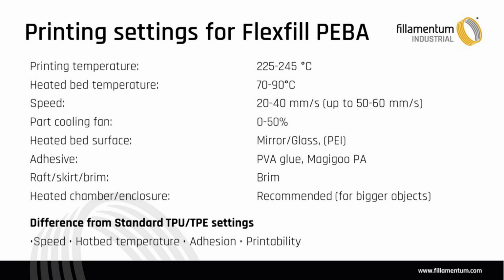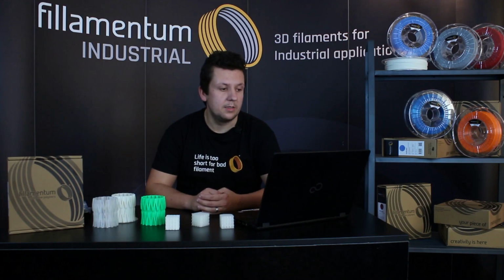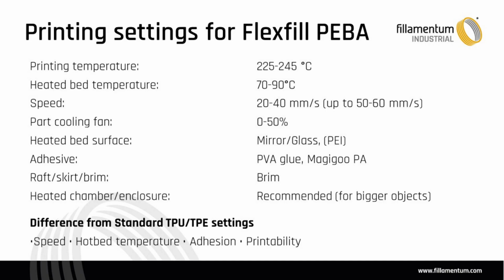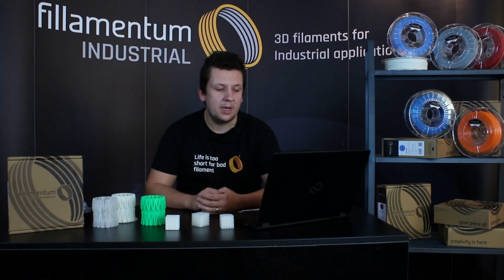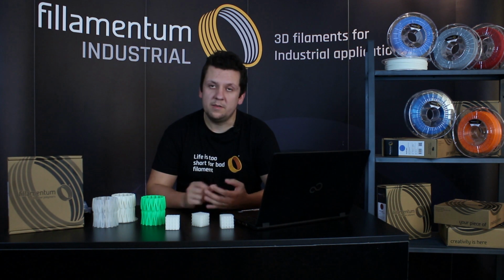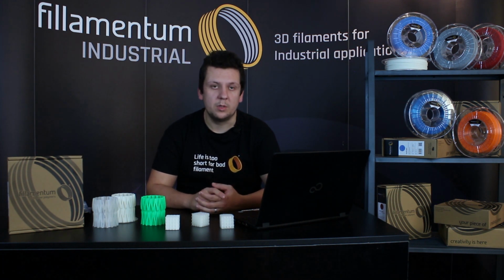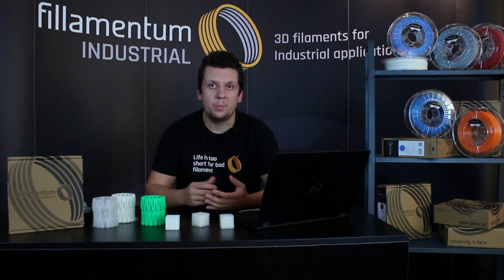And what also differs from the basic settings is the speed, because this material can be printed with higher speeds than the basic Flexfills. 20 to 40 millimeters, also up to 50-60 millimeters per second. Part cooling fan 0 to 50% to avoid shrinkage of the material. For the heated bed surface, definitely recommend mirror or glass instead of PEI. Better adhesion you have, and it's better for your printing. For the adhesive, we would recommend PVA glue stick or Magigoo for polyamides, and definitely quite a big brim around the object if you are printing larger parts is necessary.